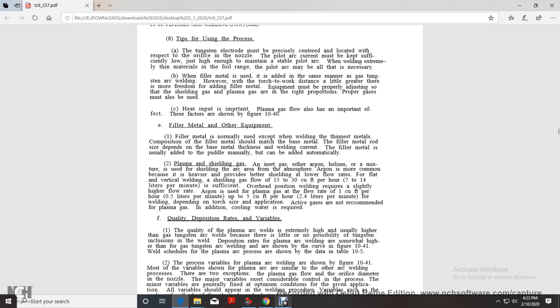Plasma gas and shielding gas are either argon or helium mixtures, shielding the arc from the atmosphere. Argon is more common because, being heavier, it provides better shielding at lower flow rates for flat and vertical welding, with shield gas flow of 15 to 30 cubic feet per hour. Overhead position welding requires a slightly higher flow rate. Argon is usually used as the plasma gas, with a flow rate of 1 cubic foot per hour up to 5 cubic feet per hour, depending on the torch and the application. Active gases are not recommended for plasma, and cooling water is required.